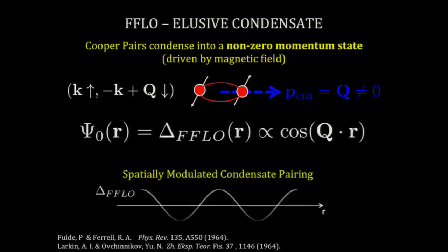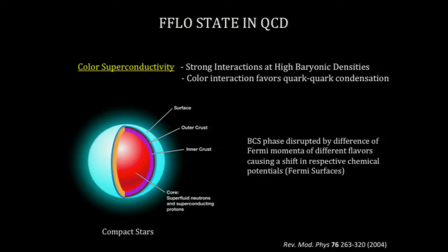And in this scenario, the superfluid state's order parameter, or you can think about it as the gap function, is going to modulate in space. So this is part of the family of the pair density waves, in which the order parameter of the superfluid, that phase which breaks the U(1) gauge symmetry, has a spatially modulated signature. And just to bring it back, there are also theories in quantum chromodynamics for how you can get one of these pair density waves in a compact star. So good connections.